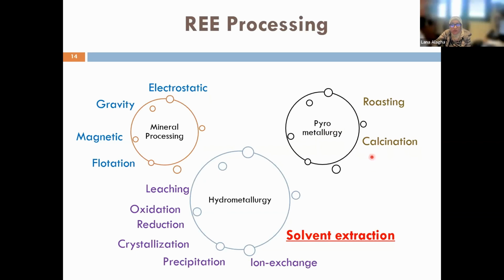So sometimes roasting is done before leaching, to enhance the leachability or solubility of the material. And sometimes calcination is done for feed preparation, in mineral processing or hydrometallurgy, to remove carbon-based material.